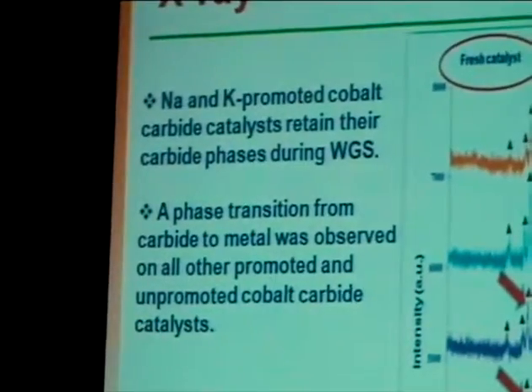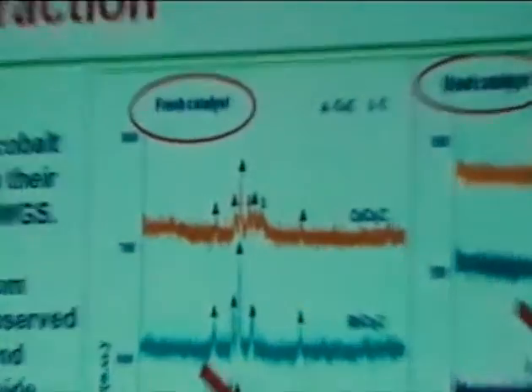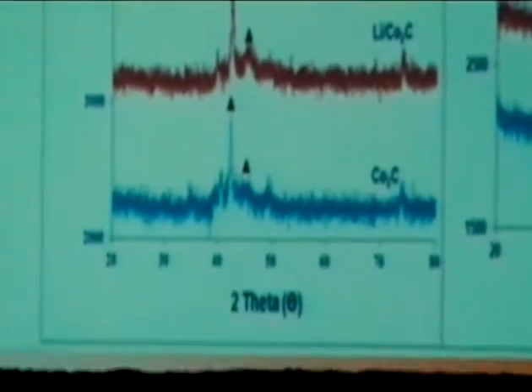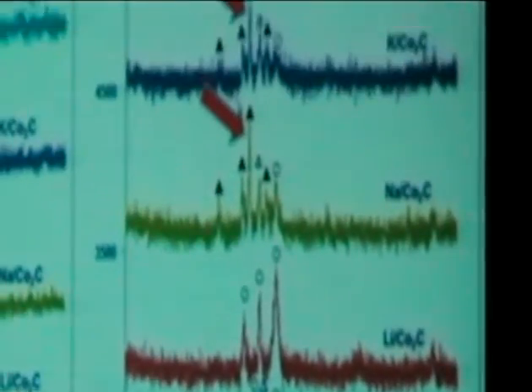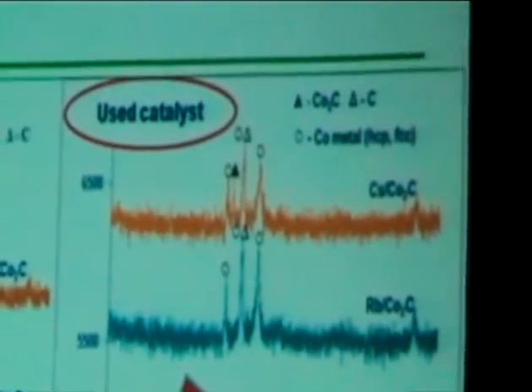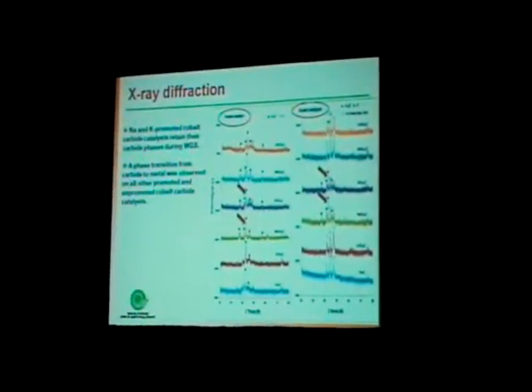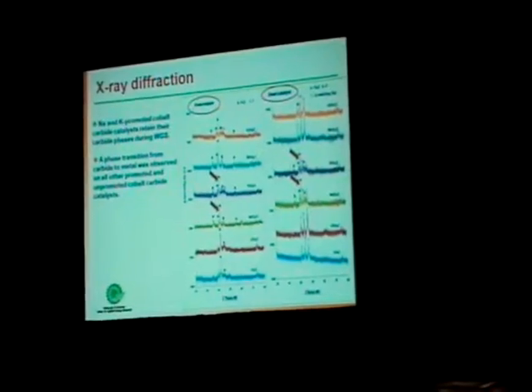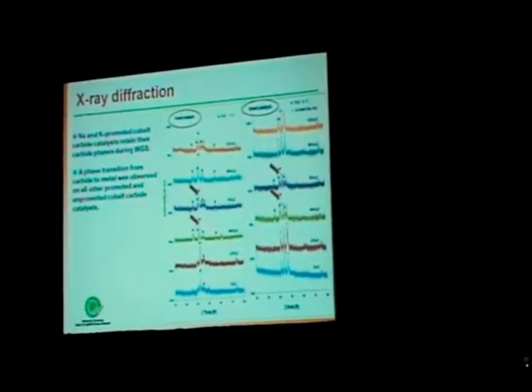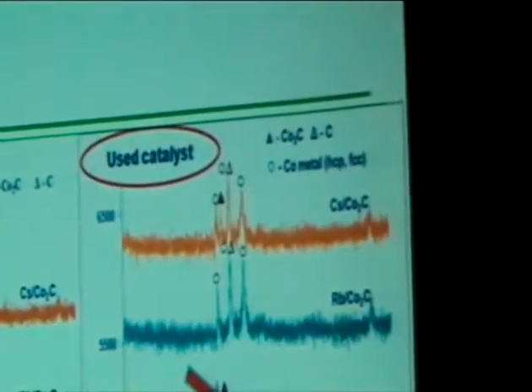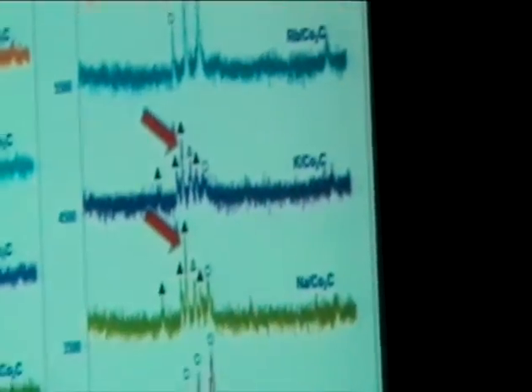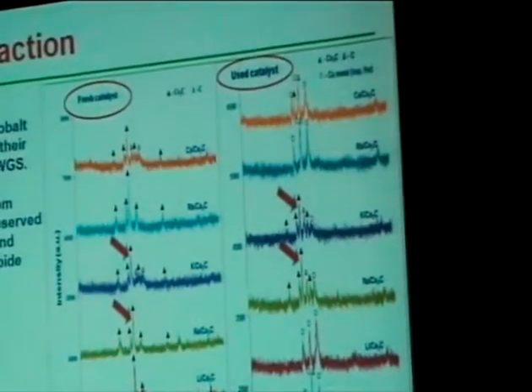And here, I'm trying to compare the fresh and the used catalyst. What we did was, once we completed the run, we passivated the catalyst and took it for XRD. And what we have seen here is that the phase changes are clearly visible. When we have no alkali, you can see a clear change in phase from carbide to metallic character. It is not completely metal, but it still contains some carbon as well. So, when you start with the carbide, it goes to a metallic phase under this condition.